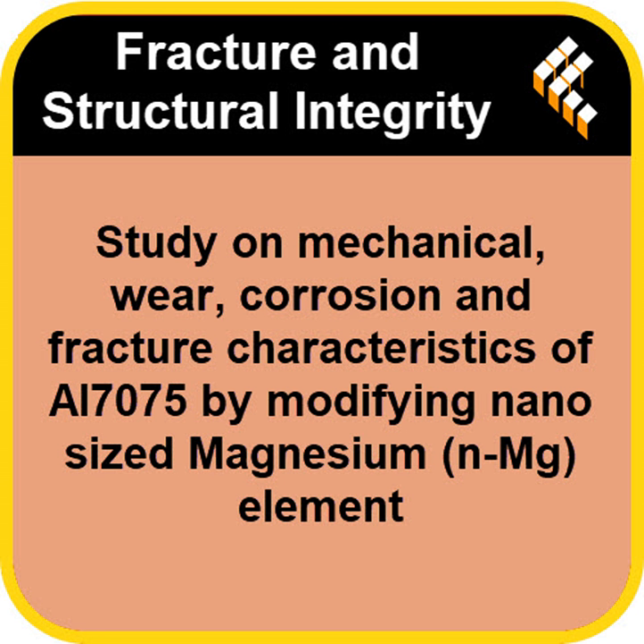Let's pivot now to the potential price tag of that rigidity. Toughness. And this is where the dilemma really begins. When researchers measured impact strength, the ability to absorb a sudden shock before failing, the results were dramatic and concerning. As the nano-Mg content went up, the impact energy went down significantly. The impact energy fell from 28 joules in the base alloy down to just 18 joules in the modified samples.